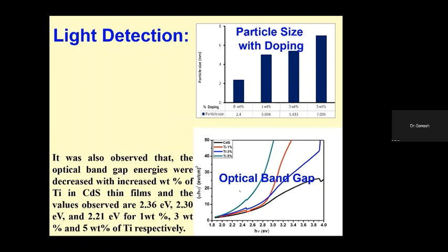This is the optical band gap. Here for Ti 1%, 3% and 5%, we have observed the energy band gaps. They are 2.36 electron volt, 2.30 electron volt and 2.21 electron volt for 1 weight percent, 3 weight percent and 5 weight percent respectively.